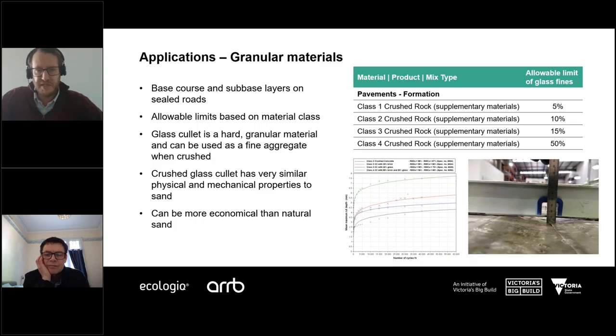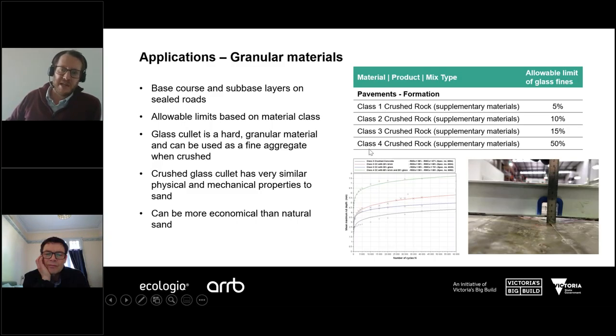But if we're considering sprayed sealed roads, there's certain acceptable limits on the amount of recycled crushed glass that can be used in different classes of crushed rock as supplementary materials. And obviously those allowable limits reduce as we move up through the classes from the lower quality class 4 material, which we could allow up to 50% supplementary materials or fine glass fines, through to a class 1 crushed rock where we couldn't accept any more than 5%.